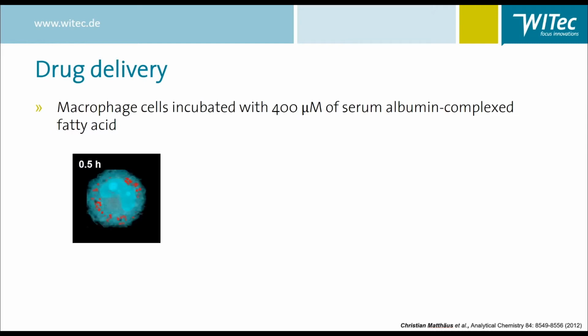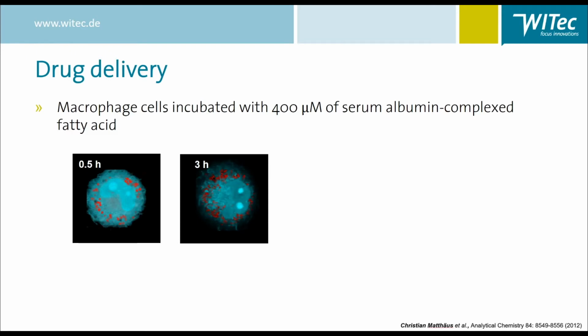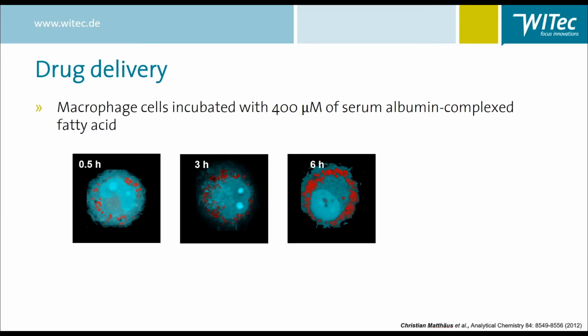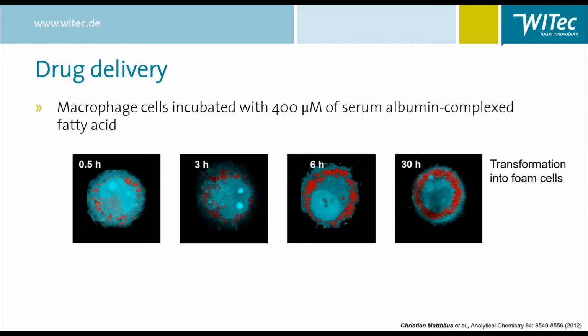For this purpose, they incubated the macrophages with different deuterated lipid species, such as fatty acids or cholesterol, and measured Raman images over several hours to observe the uptake dynamics and to visualize the intracellular distribution. This Raman image shows a cell after 30 minutes incubation with a fatty acid. A few lipid droplets are visible in red color. The rest of the cell is kept in blue. After 3 hours, the number of new lipid droplets has increased significantly, and again after 6 hours. Finally, after 30 hours, the Raman image revealed that the region of the cell around the nucleus is dominated by the lipid droplets. The macrophage is transformed into a foam cell.